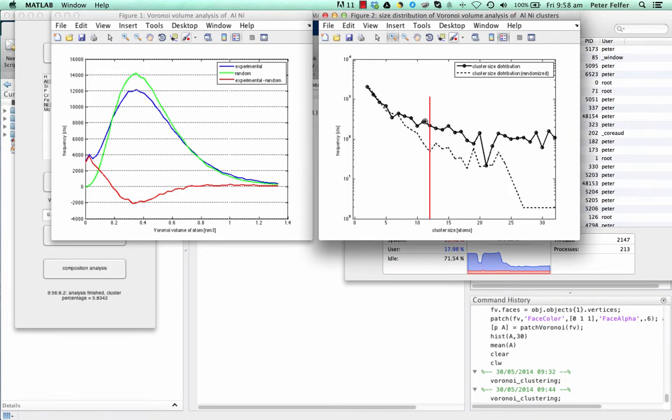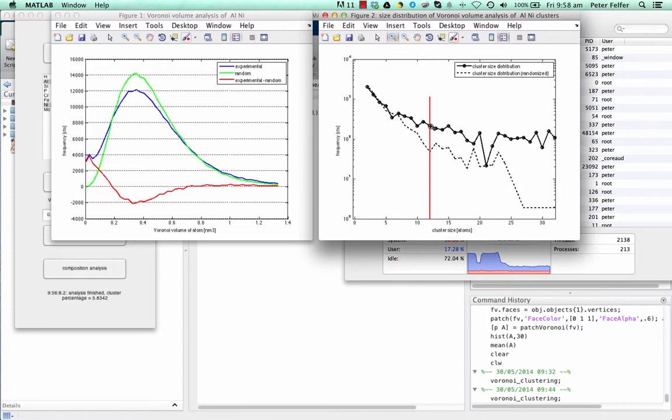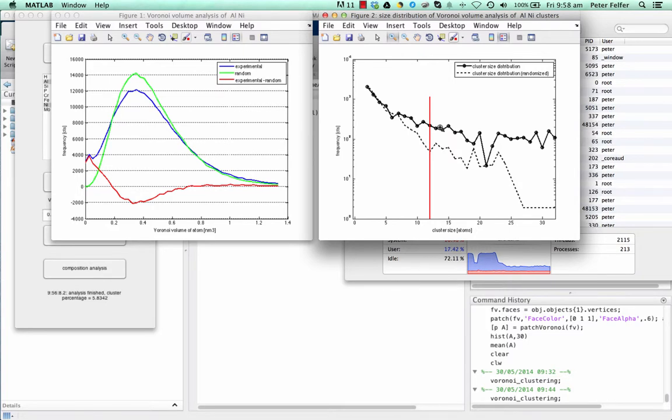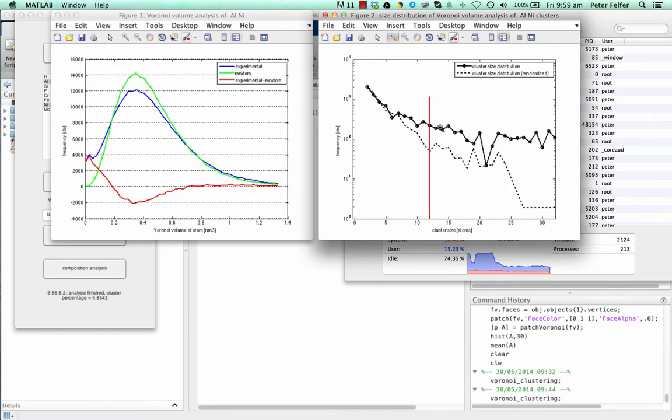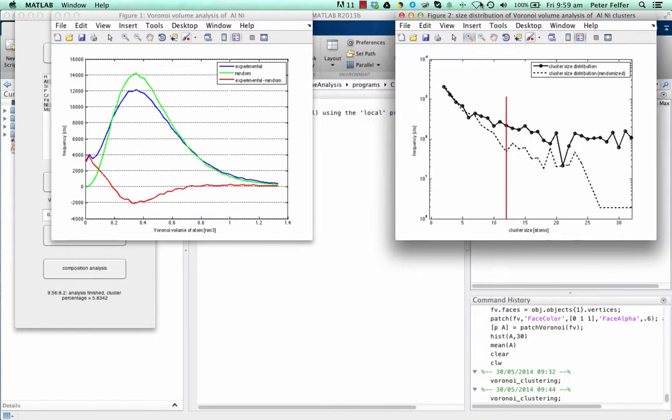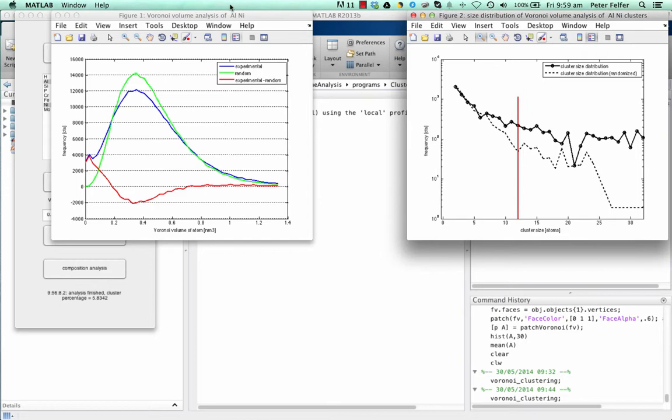Most of the random clusters are very small. That's where it actually matches up with the actual cluster size distribution. The cutoff point is where the amount of randomized clusters is less than half of the amount of the clusters in the non-randomized data. Which means that if I have a cluster in my data, it's more likely to be an actual cluster than a random cluster. That's what it really makes for the cutoff point. That is the entire analysis.